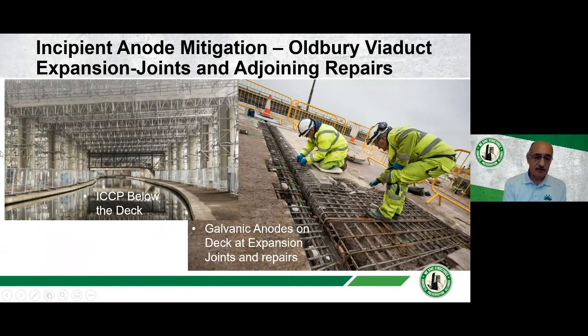The way that they dealt with it was the substructure, which is holding up the road on the top, the slab, which included the columns and the cross beams, were cathodically protected using an ICCP system, whereas the deck was protected by using galvanic anodes. Again, you have the expansion joint, and this is where the corrosion would have been happening because the water was seeping down. So all these needed to be repaired. Once again, you're going to have new concrete being cast against the older concrete, which would probably contain some chloride still, and therefore you're in need of protecting this edge, and a line of anodes were placed at 450mm spacing. There were also other patch areas that needed to be repaired as well, and as the suggestion, the anodes would go all around the edge of the repair to protect surrounding concrete.